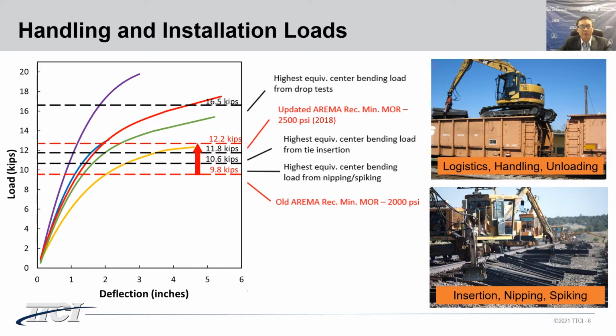The 5 curves in the plot represent the center bending load versus deflection curve for 5 composite tie types. The black dashed line shows the peak equivalent center bending loads calculated from these tests. The equivalent center bending load from the AREMA recommended minimum modulus of rupture, MOR, is also shown for comparison. MOR is a measure of the ultimate bending strength of the tie.